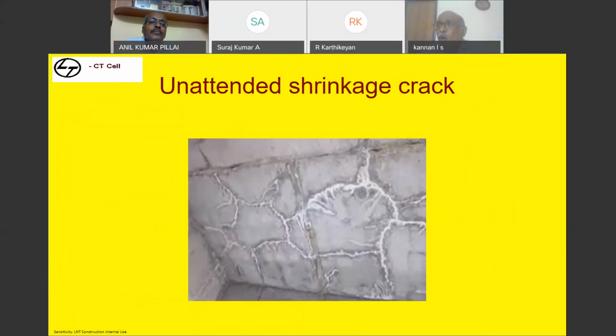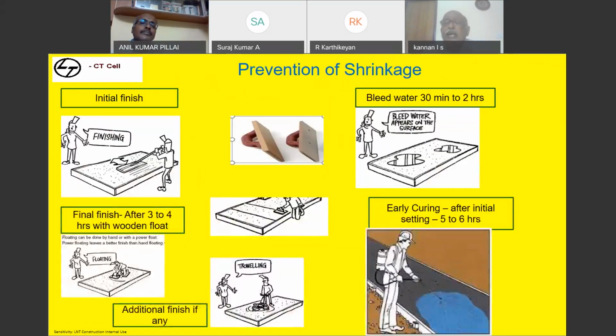On removal, you will find white patches. These are all calcium hydroxide leached out by water. In some cases it gets closed. Sometimes even the slab can leak water. So this is a bad sign, even though structurally there is nothing wrong with this, but from the acceptability point of view, everybody will panic on seeing such cracks. So to avoid this, as I said, secondary finish is a must.